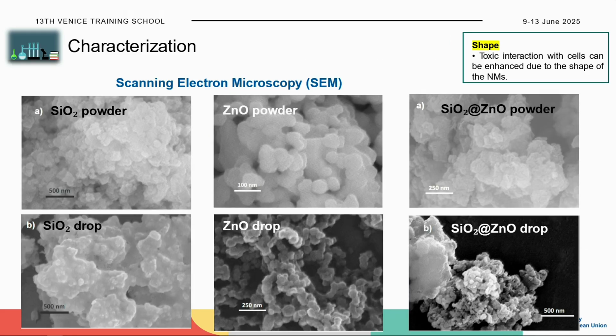Of course, we look at the shape also with SEM microscopy. So here you have an idea about 2 different types of samples. One directly from powder, where we look at the powder sample, and then also we prepare a dispersion that we deposit as a drop for being analyzed by SEM. What we observe is that more or less we have the same characteristics and the same shape, I would say, between, again, silica dioxide nanoparticles alone and the advanced material that is made also by zinc oxide.